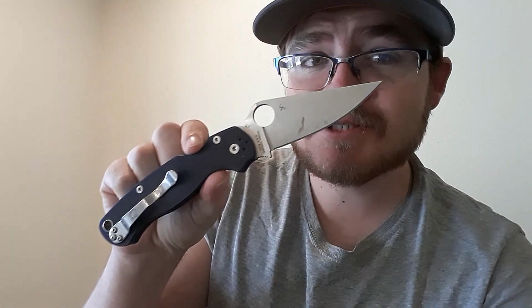Yeah, very cool. Quick interjection. When it came to the S110V, when I was scratching quartz with this, the quartz was taking steel off of the knife blade. However, when I was scratching this orthoclase crystal, there was no steel coming off. So they weren't scratching each other, which makes me think they're close to similar in hardness. Now, this blade did scratch this piece of feldspar a little bit. Could be because of inclusions or elements mixed in with the chemistry. This also is perthitic. You can see there's a little bit of exsolution, probably plagioclase, so that could have affected the hardness there.